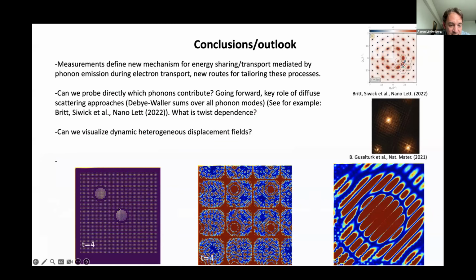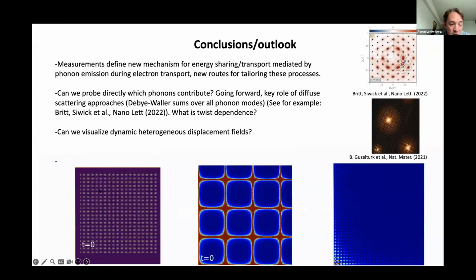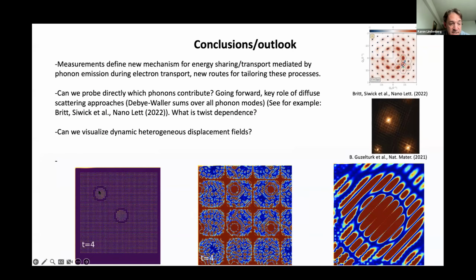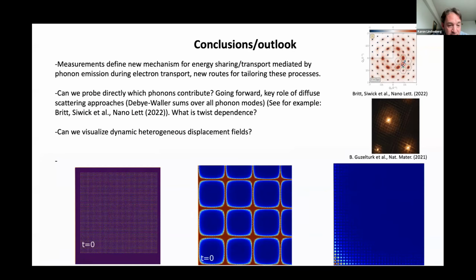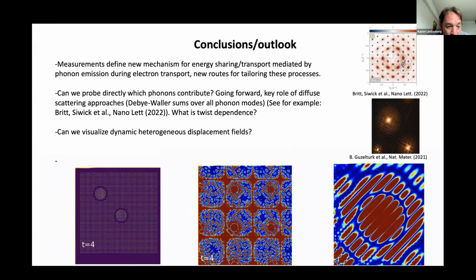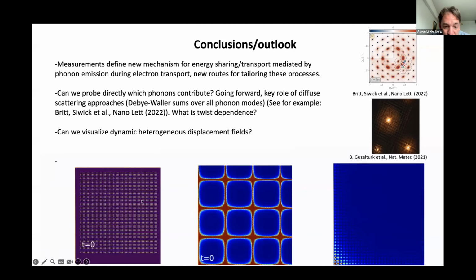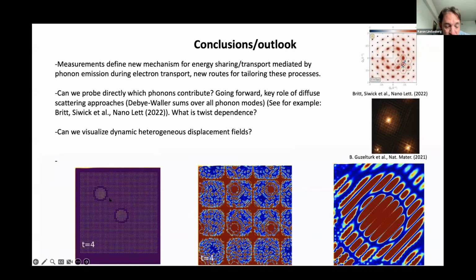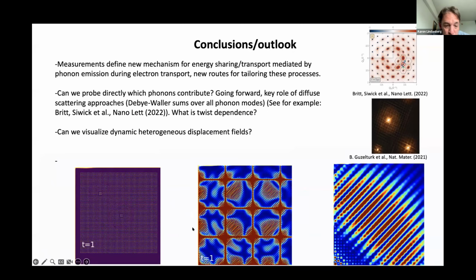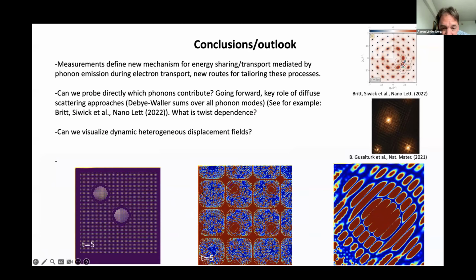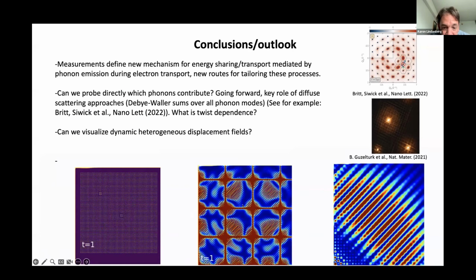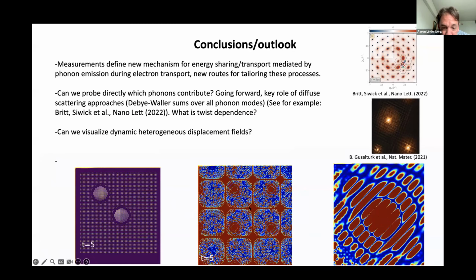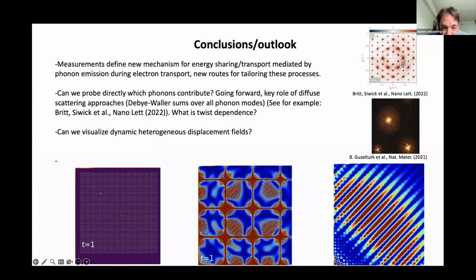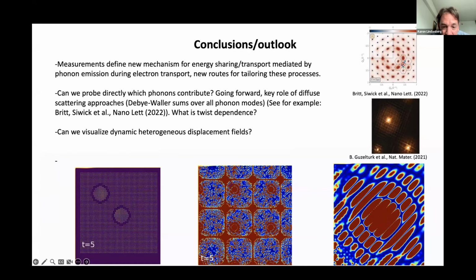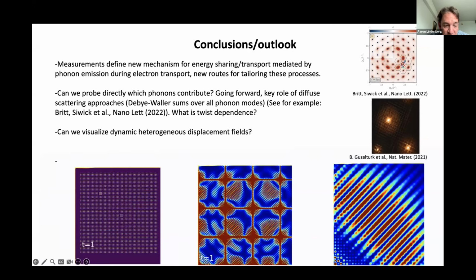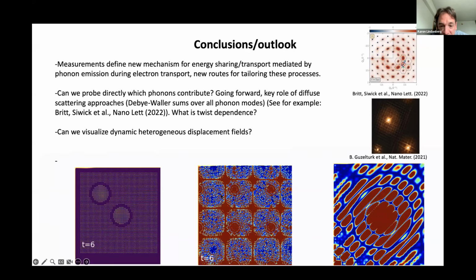So here these are kind of like two nucleation events or two local defects coupling to their environment as an expanding acoustic strain field. And this strain field is then directly related, essentially the Fourier transform of the structure is what you measure when you do a diffraction experiment. And you can see the amazing complexity of the diffraction pattern. These are the actual Bragg points in the structure. And then everything else here is essentially encoding information about the heterogeneity.